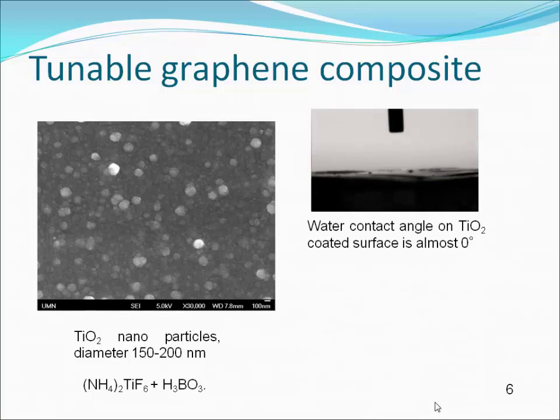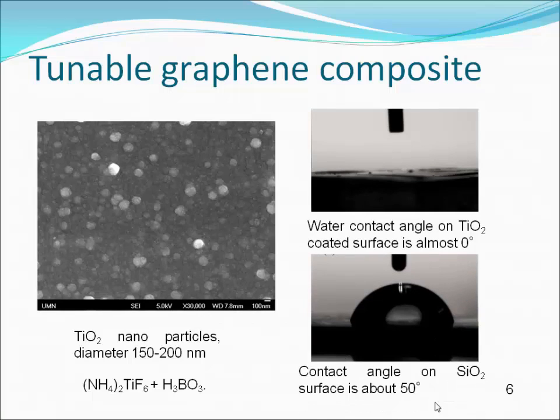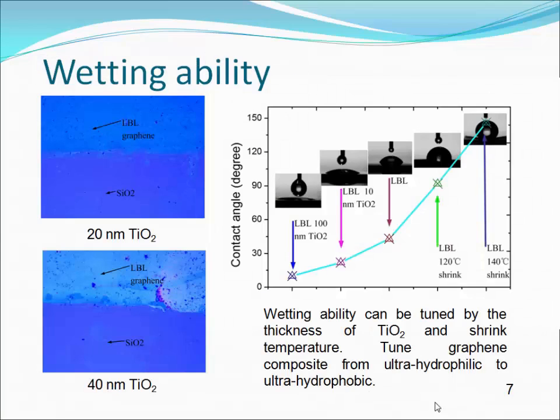The water contact angle on titanium oxide coated surface is almost 0 degrees, indicating super hydrophilic. On the other hand, the contact angle on silicon oxide surface is about 50 degrees, so it's relatively hydrophobic. The layer-by-layer graphene film with different thickness of titanium oxide layer will have different colors on silicon oxide surface and different water contact angle. For example, if we increase the thickness of titanium oxide layer from 10 to 100 nanometers, the water contact angle of this graphene film will reduce to about 20 to 10 degrees.